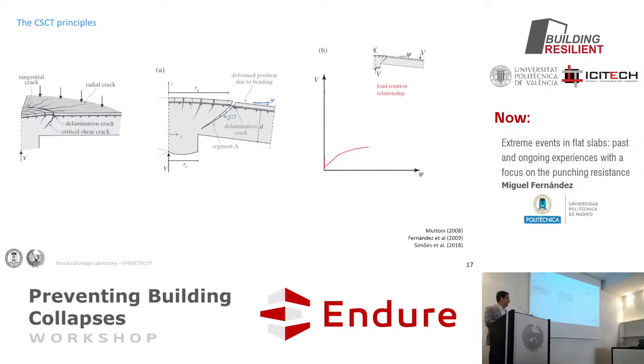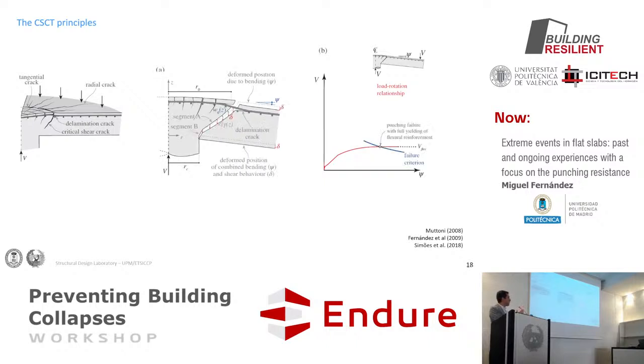So the crack will disengage, and then we will have a penetration of the column. This is exactly the video that Sarah was showing. We can start with a crack which is opening in a flexural manner, and then it punches, it penetrates. This is what we call a two-parameter kinematical model, depending on the rotation and also on the penetration of the column. And this is giving that even if you are limited by your flexural resistance, you will punch.